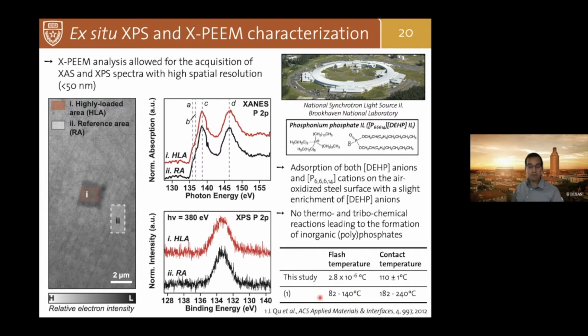Whereas in the case of the experiments reported in the literature, since they were sliding at very high speeds, there was a drastic increase in the contact temperature, which results in a temperature that is very close to the degradation of the ionic liquid. So the stress in the case of the experiments reported in the literature probably is enough to lead to the reaction of the ionic liquid on the surface and the creation of a boundary layer.